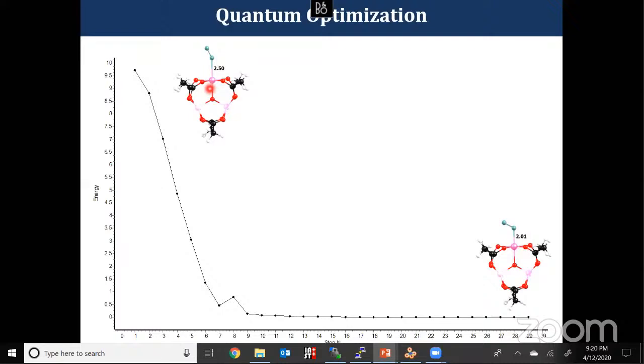But really, if you want a real structure whose bond parameters and everything match the experimentally available structure, we need a very good functional as well as method to do the optimization process. Once we get the optimized structure, normally we do a frequency calculation in order to confirm whether it's a minimum structure or not. If we don't get any negative frequency, that means the structure is fully relaxed on the potential energy surface.